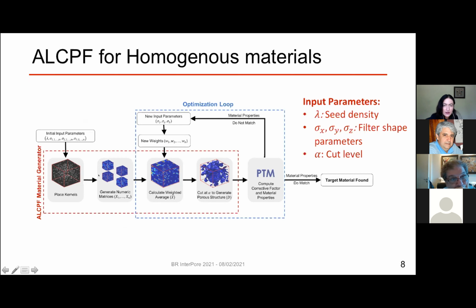So again, this graphic is basically the skeleton of the method. We create a domain, we throw in the kernels or the inclusions with the density of lambda, and we produce the first Poisson field. Based on this one, we generate 4 domains. Then we do a weighted geometric average, and we create one more. Then we compute the material properties. If the material properties match the target, we're done. If not, we set new input parameters. We modify these shape factors, we produce new shapes, new weights, and we iterate until this is done.